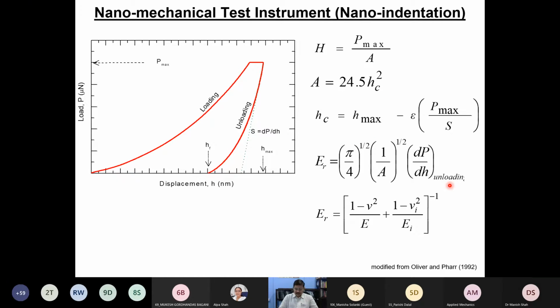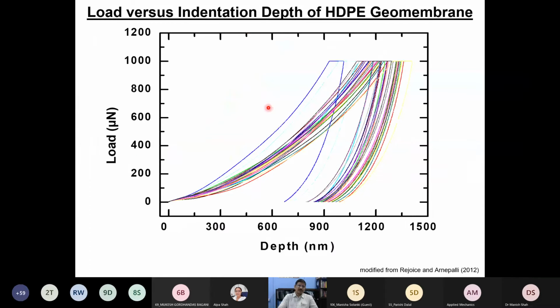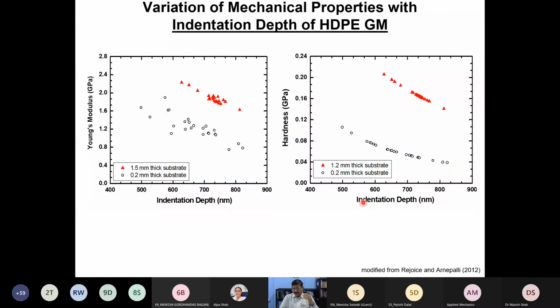Of course, at later dates, the entire polymer may be subjected to photodegradation. So these are some of the nano indents we made on a small, tiny piece of polymer. We made around 25 nano indentations on this, and more or less everything is showing the same. If you look at the size of the sample, what we need to make 25 indents is something like a 25 paisa coin, not more than that. So it's a very, very precise measurement that we are able to do.